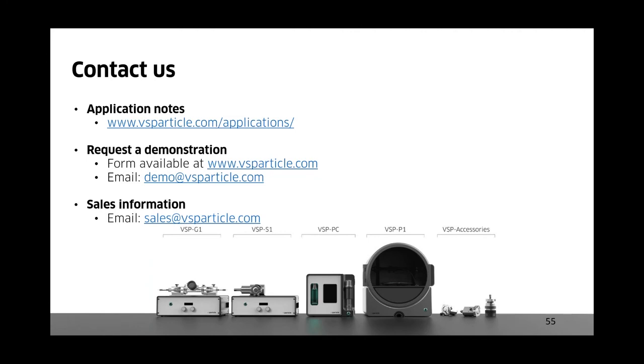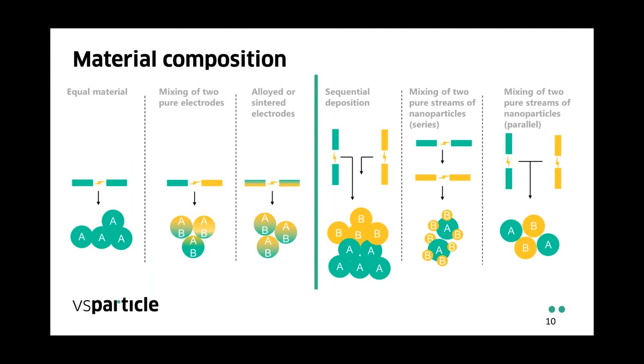Moving on to the second question: what is the most promising approach to prepare alloyed nanoparticles? This is something I'd shown in one of the slides. The most effective way is by mixing and matching electrodes, as we do here in a single G1 nanoparticle generator, but what you'll get is a mixture of compositions in your final nanoparticles. The most effective way to really get alloyed nanoparticles is by having your electrodes pre-alloyed, and then using those electrodes to generate your nanoparticles.